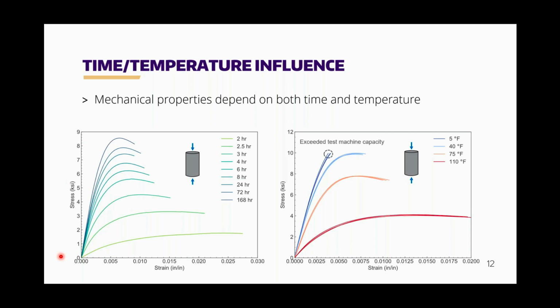On the left, you can see the rapid development in strength and stiffness. On the right, you can see the dependence of temperature. At a low temperature, the material is stiffer and stronger. It actually exceeded the test machine capacity in this case, which is why those lines suddenly end. As you increase the temperature up to, in this case, 110 degrees Fahrenheit, you can see that the compressive stress-strain behavior becomes much more flexible and loses some capacity. And that just has to do with the nature of polymer concretes and their chemistry.